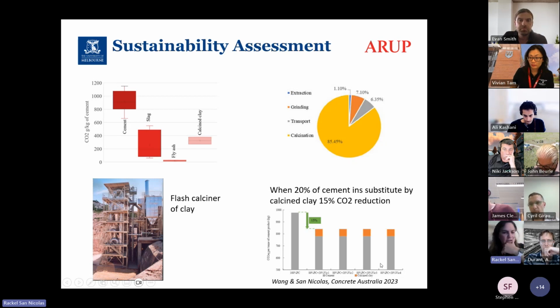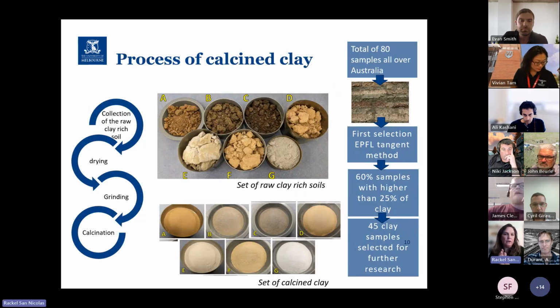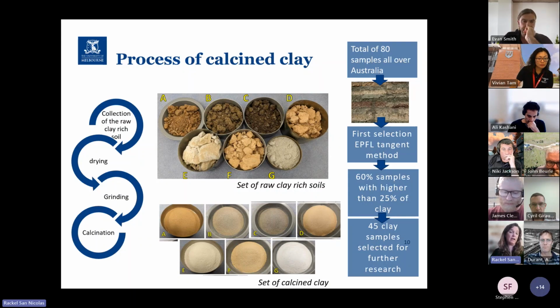This is just the result of a study. Several Australian clays have been gathered and tested, and we did an analysis of it. Basically, if you are substituting about 20% of the cement in concrete with calcined clay, you are reducing the embodied carbon of your concrete per ton by 15%. So the process of calcined clay is really simple, and I summarize it here. Basically, you collect the material, you usually dry it, you've got a grinding phase, and then the calcination. Depending on what technology you are using for the calcination, sometimes you have to have another grinding afterwards. But as I said, usually the whole bulk of the embodied carbon is due to calcination.